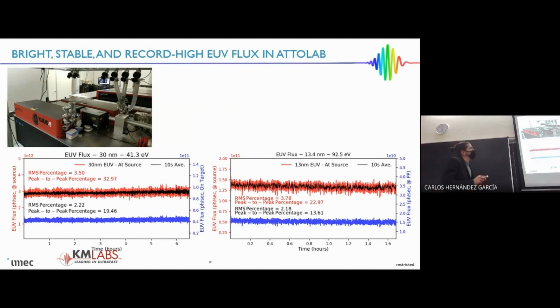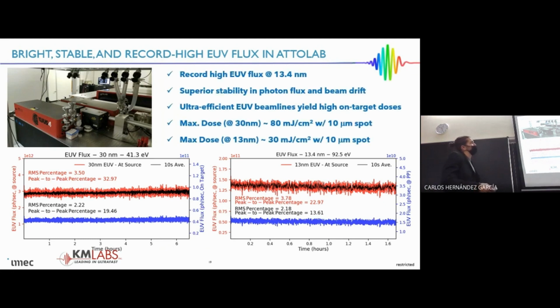Here you can see this is generating harmonics at around 30 nanometers, and we have really quite high flux from these systems and very nice long-term stability in the lab. Also at 13 nanometer, we can deliver almost 10 to the 10, 10 to the 9 photons per second on target. This was when the system was new, so that's a little higher than now. This gives us a lot of flexibility in these spectroscopies, and a lot of room to play around with doses for these photoresist studies, and really gives us a nice robust system.